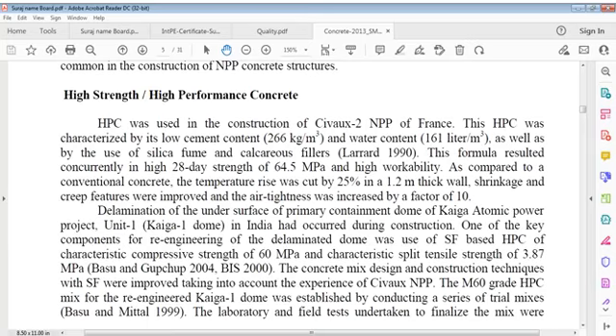High performance concrete was used in construction of Civaux NPP of France. It was characterized by its low cement content, 266 kg per meter cube, and water content 161 liters per meter cube, as well as by use of silica fume and calcareous fillers. This formula resulted concurrently in high 28 days strength of 64.5 MPa and high workability. As compared to a conventional concrete, temperature rise was cut by 25% in a 1.2 meter thick wall, shrinkage and creep features were improved, and air tightness was increased by a factor of 10.